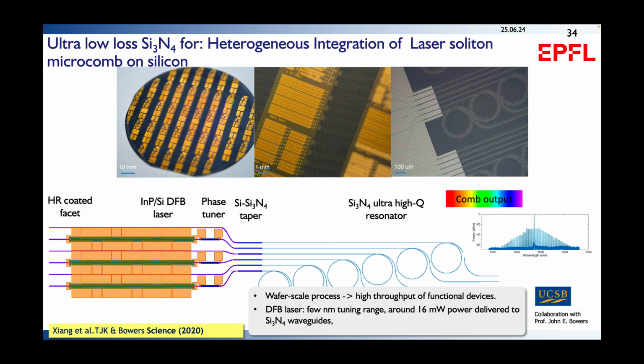Now, to give an example, if you want to dream further, what's the most compact kind of chip-scale comb that you can possibly imagine? This is some work we did with John Bowers' group, where the pump laser was heterogeneously integrated. What you see here is a silicon nitride wafer. There's a so-called interposer made from silicon to take the light from the low-loss silicon nitride into a III-V epi that has been structured to make DFBs. The entire device has a length of 500 micron and a width of 100 micron, so literally it fits on a needle tip.